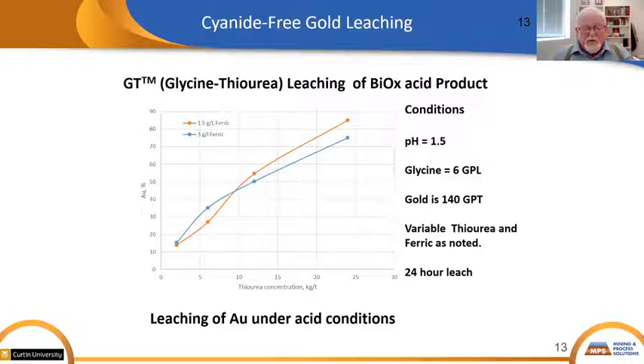Now, this is a modification of an old method that has never been used commercially because of the very high reagent consumption caused by excess ferric. And if you don't have ferric, the gold doesn't go into solution, but it destroys the thiourea that makes the process uneconomic. We have modified it by the addition of glycine, and it does constitute a cyanide-free process to deal with acid leach products and can save the considerable cost of lime to neutralize and raise the pH to the safe point around 10. Glycine possibly prevents the oxidation of the thiourea by combining with the ferric to form ferric glycinate. And we're doing a great deal of research at the moment on this very interesting process.